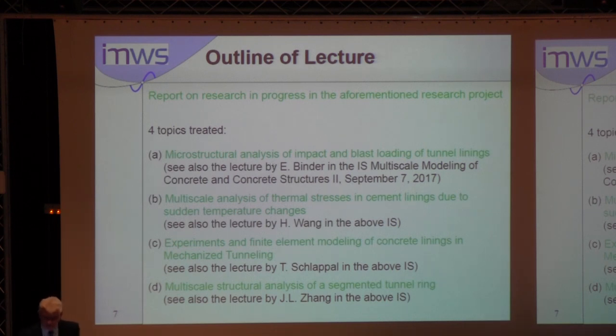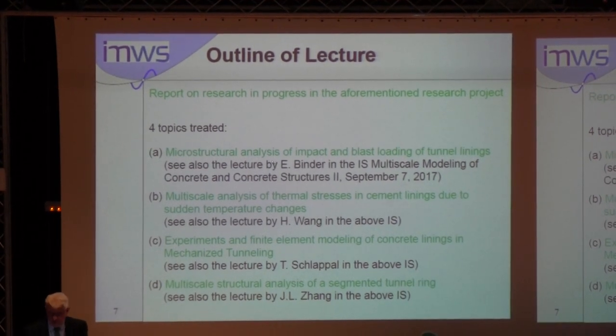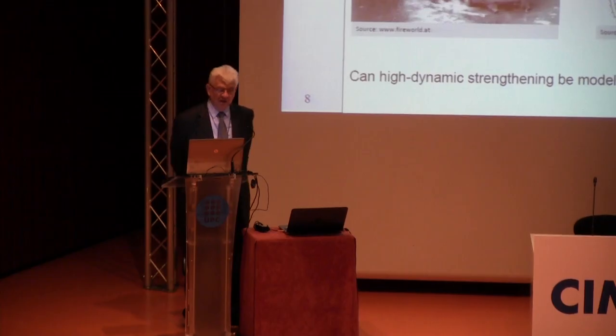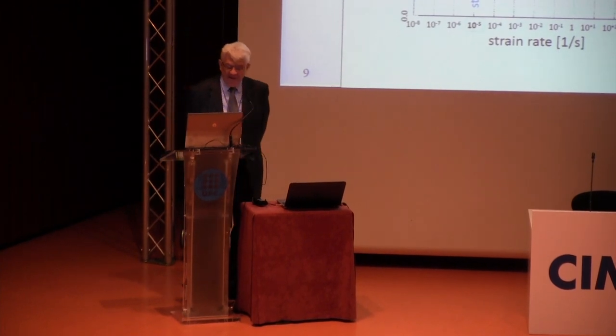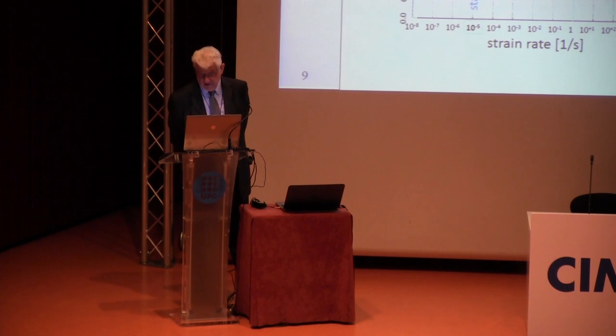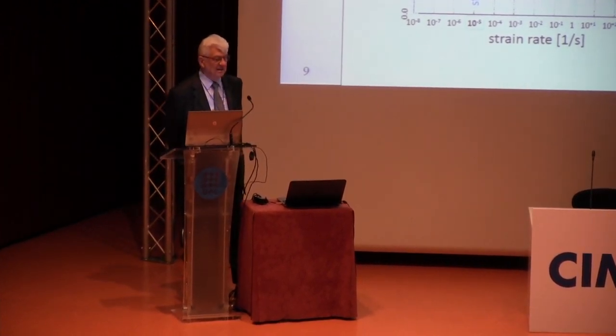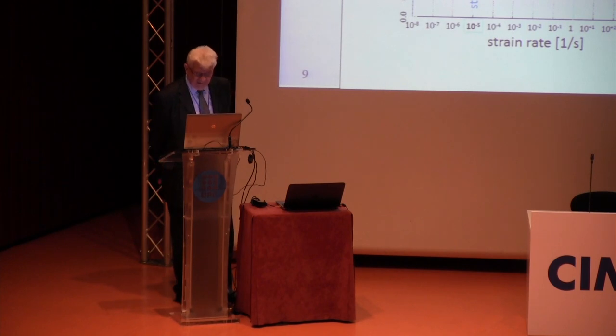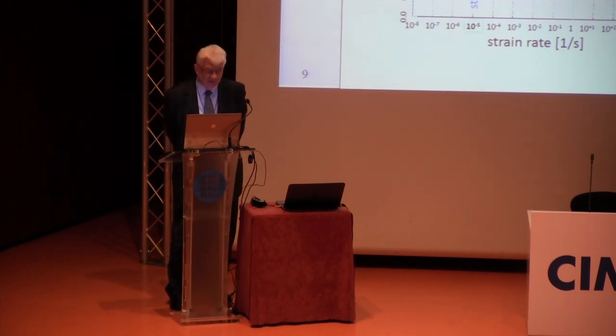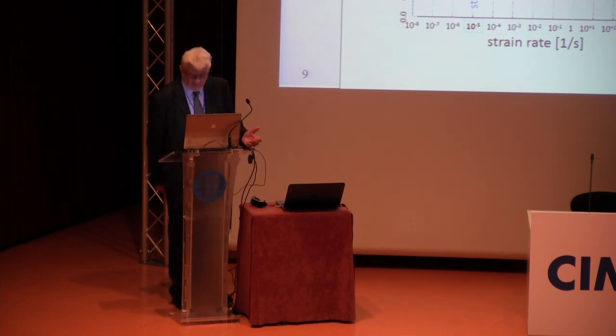The motivation for the first part: the topic is Treatment of Exceptional Load Cases in Tunneling by Means of Multiscale Analysis. Traffic accidents and explosions result in high dynamic loading of concrete linings. The question is: can high dynamic strengthening be modeled by multiscale analysis? Experimental evidence shows that strength increases with increasing loading rate. The figure shows the dynamic strength increase factor DIF, equal to the ratio of dynamic strength over static strength, confirming that strength indeed increases with increasing loading rate.